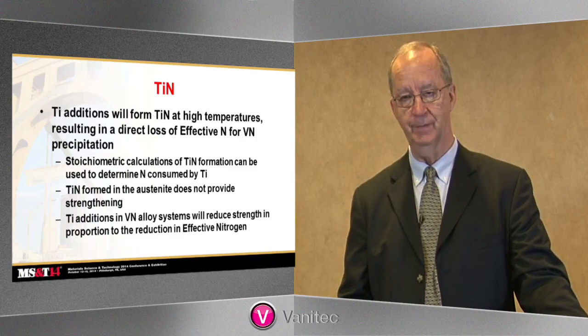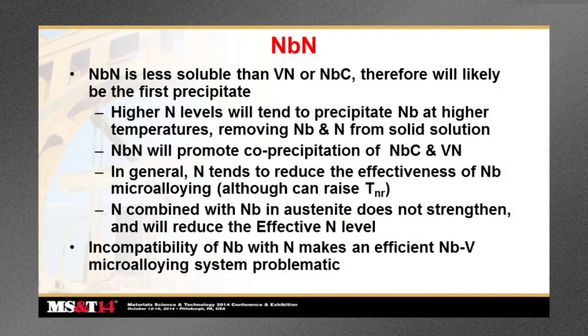Now, when we look at niobium nitride formation, we know it's less soluble than vanadium nitride or niobium carbide. Therefore, niobium additions will likely precipitate certainly before the vanadium, and even to some degree before the niobium carbide, depending on the carbon level, of course. Higher nitrogen levels will tend to precipitate niobium at higher temperatures, removing niobium and nitrogen from solid solution.